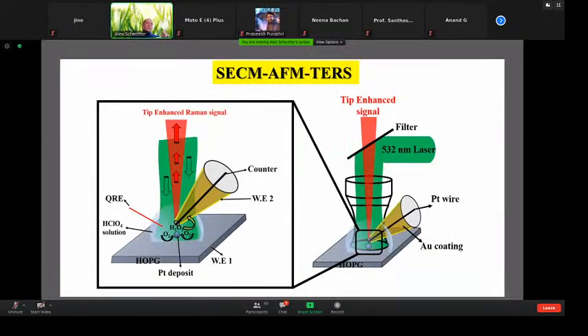And the last step was to look directly at the peroxide. Now, the peroxide is so important, we should be able to detect it. So we have applied a near field effect, what we call the tip-enhanced Raman spectroscopy, where we put the whole cell under the Raman microscope, and then we use a 532 nanometer laser to shine the edge of the tip. Now remember, the edge of the tip is made of gold. It's a glass coated by gold.